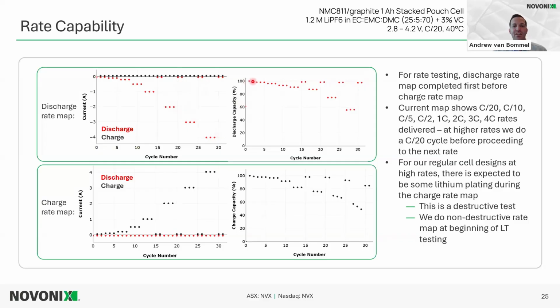So in this way, we see that there's some loss due to the kinetics of the cell. So this has about 50% discharge capacity retention at 4C rate for this build. This is not a special build for high rate or anything. It's just showing that 4C rate here.